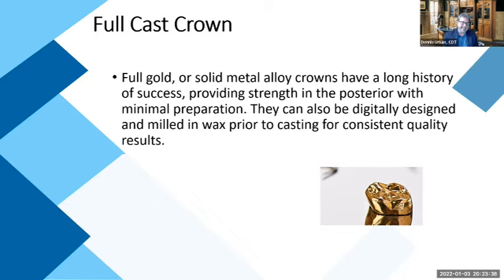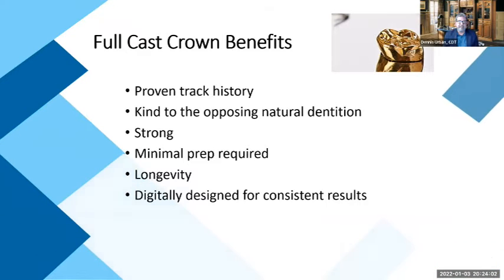And I think back now, I probably should have done it, because from what I'm hearing about the success of full gold crowns and full PFM, full gold crowns on posteriors, it's been very successful. They have a long history, providing strength in the posterior with minimal preparation, which is great. And they can also be digitally designed and milled in wax prior to casting for consistent quality results. They have a proven track record, like I mentioned, and are kind to the opposing natural dentition, strong, minimal prep, longevity is there.